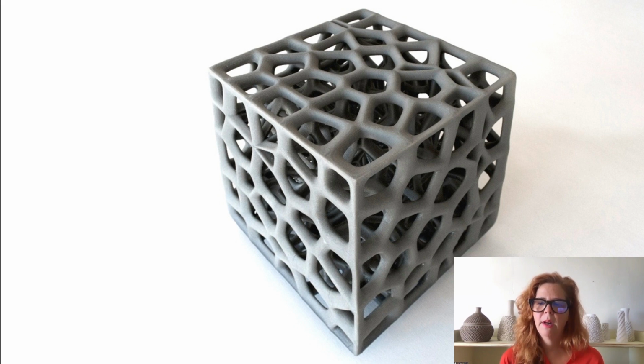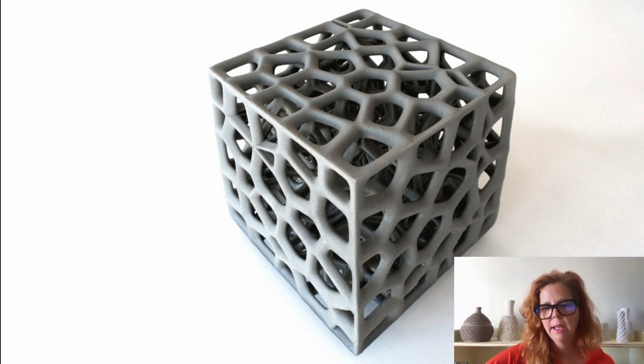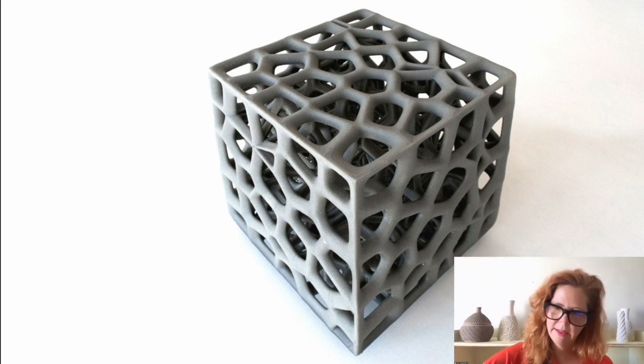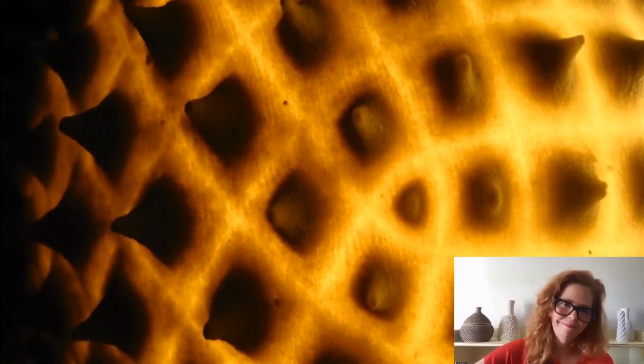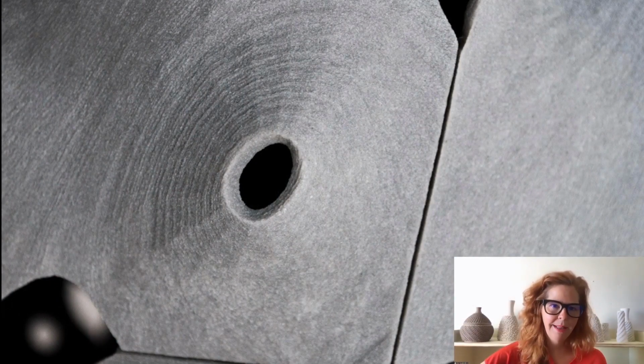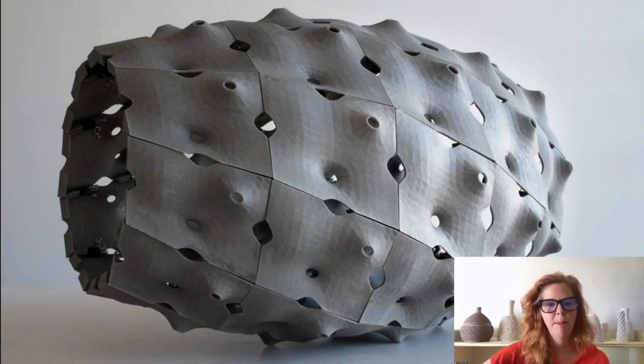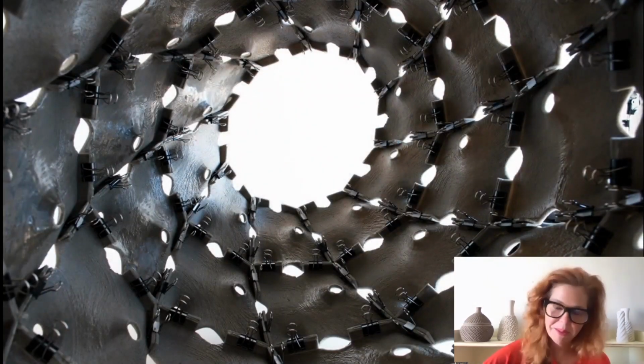Our cement polymer, after printing, has a compressive strength of around 4,700 PSI. Typical concrete is 3,000 PSI for comparison. And when printed thinly enough, it's translucent. We've experimented with different finishes. So here, for example, we've sandblasted the 3D printed cement so you can see the layers from the additive manufacturing process. We've experimented with different techniques for aggregating parts to make larger assemblies. This is an early test where we just used binder clips to hold pieces together.